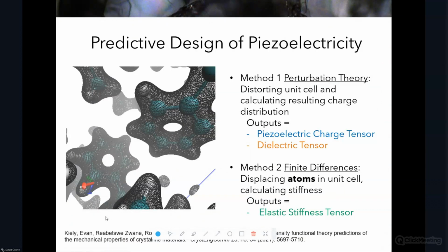But where we start with our materials is with density functional theory and with predicting their properties. So what we do for our models is we take our XRD structure, our crystallographic information file, and from that we can predict the full electromechanical spectrum of properties for our materials. That includes the remnant polarization, Coulomb per meter squared, which is connected to the dipole per unit volume that Jess was talking about. We can predict our dielectric tensor, our elastic stiffness tensor, and then all of the properties that come from the elastic stiffness tensor: the compliance, the Young's modulus, and all of those different properties.